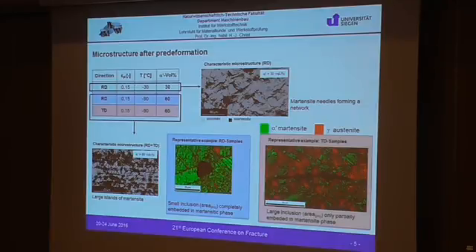If we take a look at the inclusions present in the material for RD samples, these are sections made perpendicular to the applied stress. It's a high probability that the inclusions are located in the martensite cluster. In this case, it would be something like here or something like here. EBSD measurements show such an example in this micrograph. For the TD samples with an elongated shape, here's another scale. It's not comparable to this. This inclusion is much larger. It's less probable that the whole inclusion is surrounded by a martensitic phase. This would have a major influence on the damage mechanics of this material, as we shall see in the next slides.